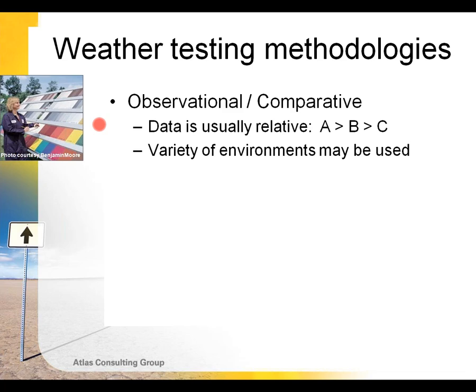There are a lot of caveats because they only really apply to one set of conditions or one location. So saying that product A performs better than B and B better than C is usually more reliable than trying to put a finite number and say that A performed 1.7 times better than B and B was only 0.2 times better than C.